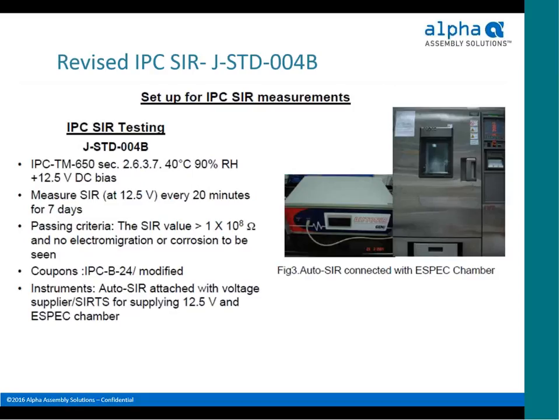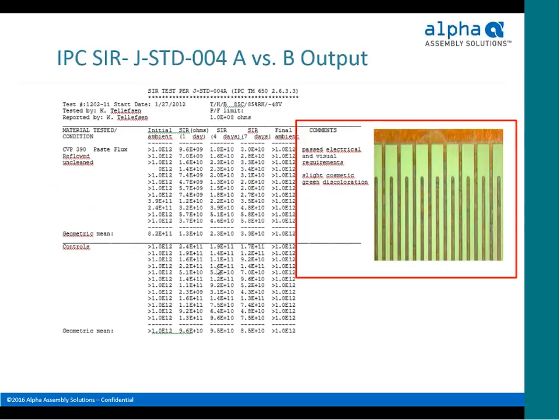The pass-fail criteria is the same. SIR value must be greater than 100 megaohms, and no visible corrosion to be seen. Coupons are the same. But now there needs to be some automated instrumentation on the test detectors attached to the test systems because of the frequency of measurements. So more robust data comes out of this test than we do with the old test methods. So we're going to compare and contrast the old versus new methods.